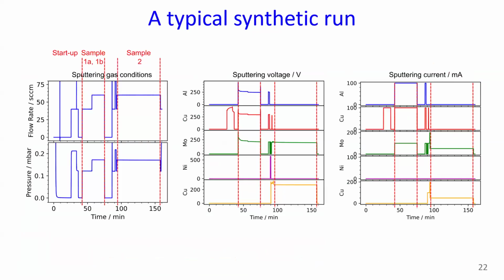The pressure, by the way, is it just air? It's argon. So argon is the sputtering gas. But you can also introduce, for example, nitrogen if you want to make nitrides, or oxygen if you want to make oxides. And different sputtering gases will affect the nucleation of the atoms. So yeah, it's pretty similar to making an SEM sample, but at a higher pressure.